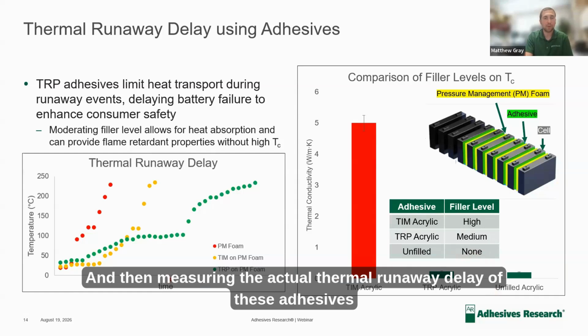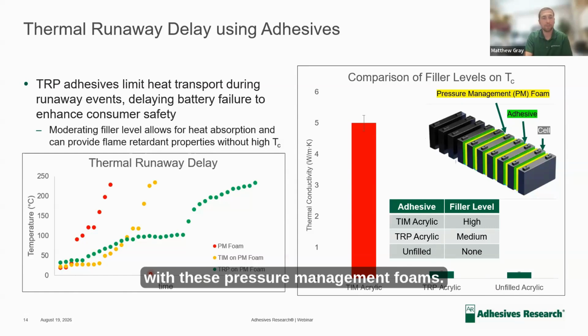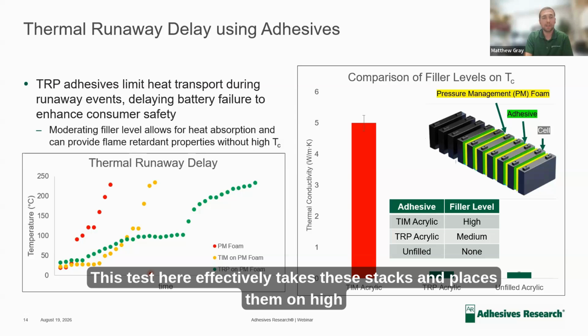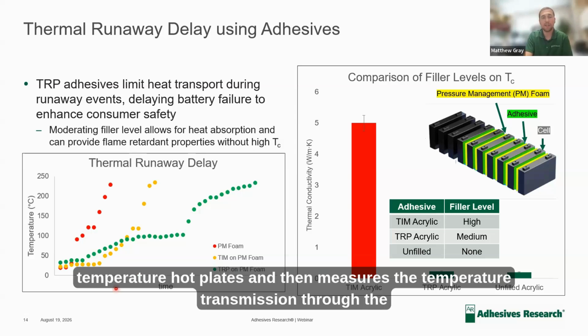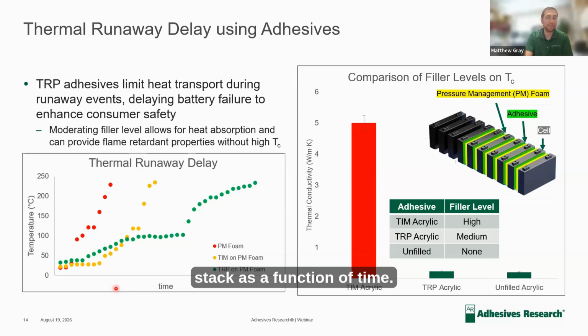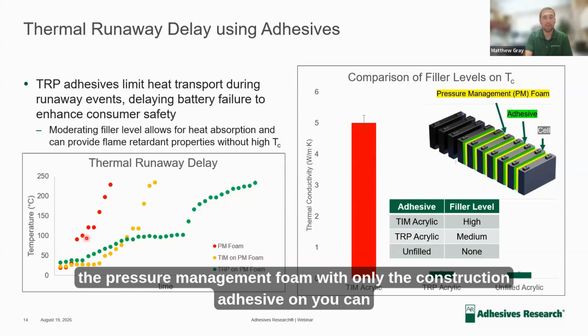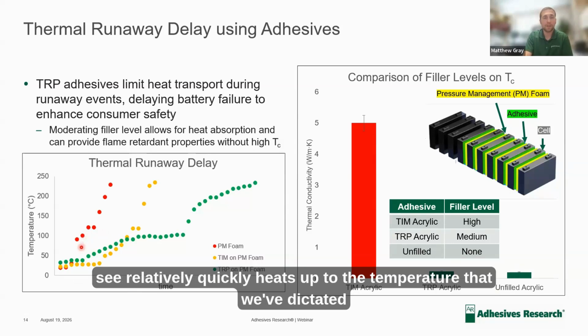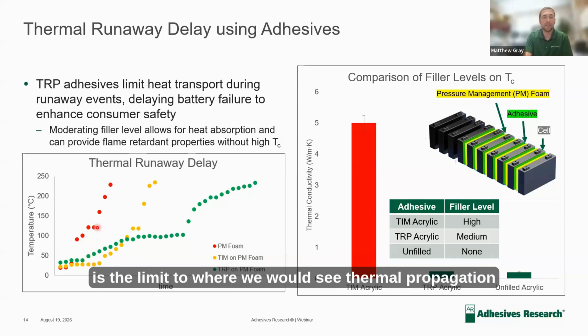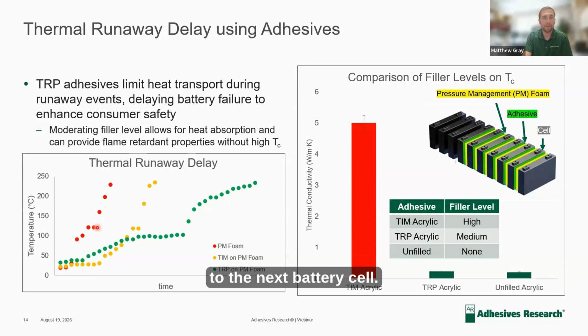And then measuring the actual thermal runaway delay of these adhesives with these pressure management foams. This test here effectively takes these stacks and places them on high temperature hot plates and then measures the temperature transmission through the stack as a function of time. So starting on the left, the pressure management foam with only the construction adhesive on it, you can see relatively quickly heats up to the temperature that we've dictated is the limit to where we would see a thermal propagation to the next battery cell.